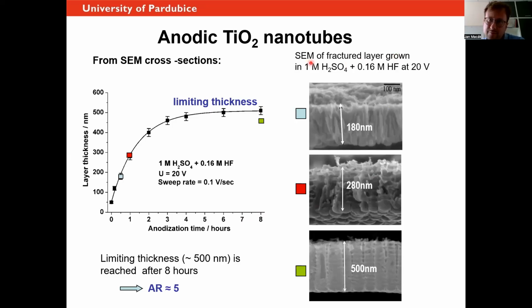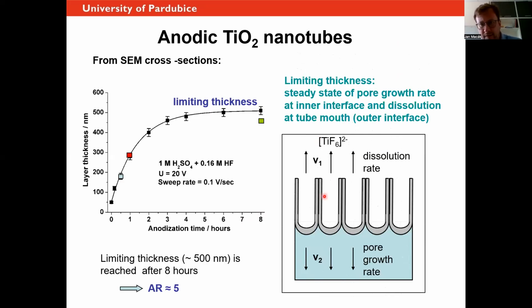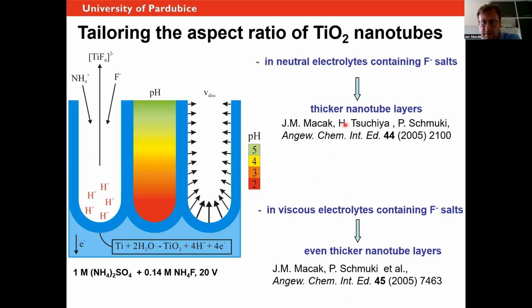So one of the key successes or one of the key steps in this material and in its development was the transition from HF electrolytes to actually fluoride salts. And the idea was to significantly enhance the tube growth, but to slow down the dissolution. It is about 17 years ago, in the lab of Professor Patrik Schmuki, we were fortunate to find suitable electrolytes, which were based on fluoride salt. So we did not use HF anymore, and we used rather neutral electrolytes.